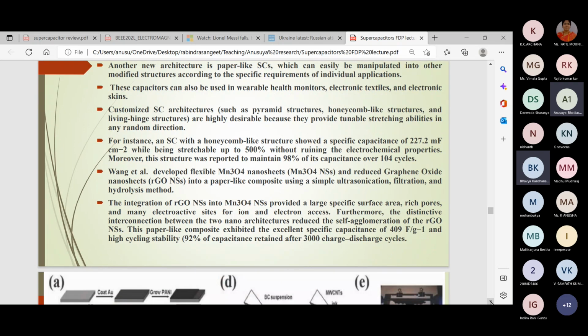So that's one method. The integration of rGO NSs into Mn3O4. NSS basically means nanostructure. Into this manganese oxide provides a large surface area, because basically the graphene oxide, as I said, all these carbon nanotube materials have a very large area. And this actually showed a specific capacitance of 409 farad per gram inverse.